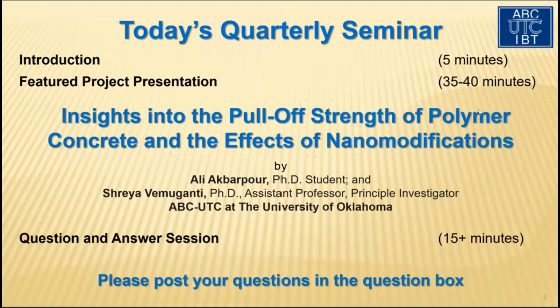strength. Okay, now another part of that question was, does the presence of chlorides after winter temperatures significantly affect the pull-off strength? So if there is seeping of those chlorides into the concrete, yes, of course, that weakens the substrate itself, and that's what we are trying to actually focus on in this study. We showed how penetration of sulphate ions, not chloride particularly, but sulphate ions, can affect the concrete itself and the bond with the concrete. So as you can see, the bond significantly reduced with an unhealthy concrete, which had that penetration of those ions. So yes, there will be significant changes.